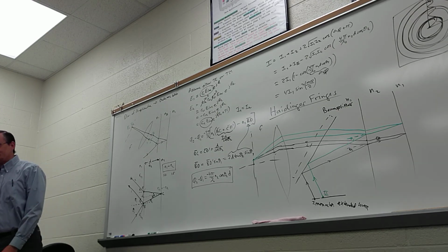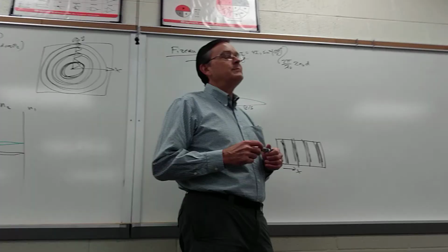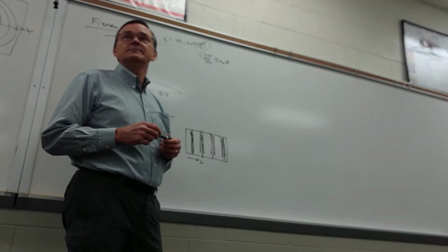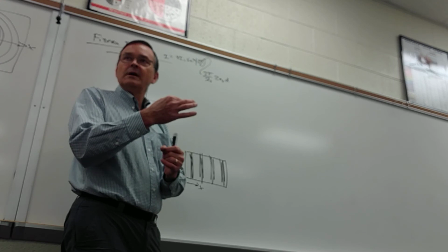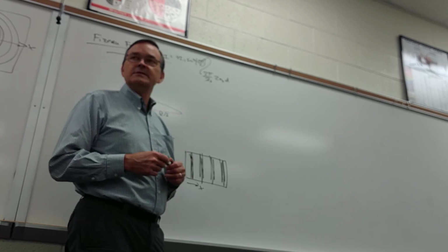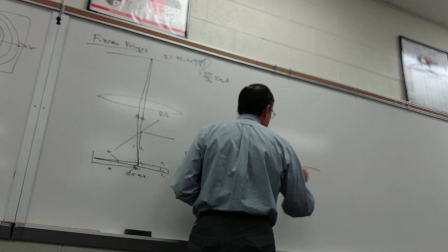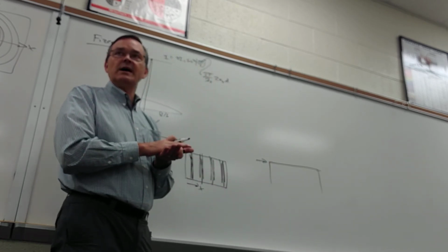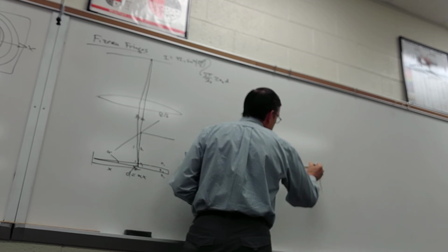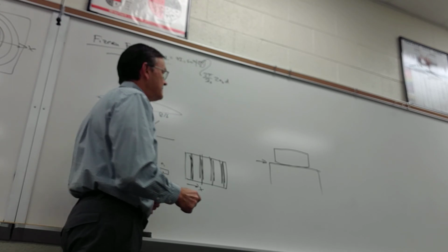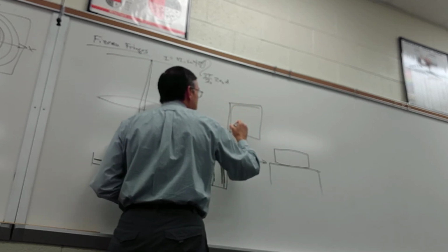When I was a grad student, one of the guys in my group would grow BSO, bismuth silicon oxide, which is a photorefractive material. It's a crystal. He'd use the Czochralski growth method and end up with a boule of material that he grew, and then he'd saw it and polish it. To know how good he did on the polishing job, he would use something like this with an optical flat. The optical flat's purpose is to have a really flat surface, so that is your reference surface. If you put one of these polished BSO crystals on here and look at the fringe pattern from this direction, with a really good polishing job you'd see fringes that would do something like this.